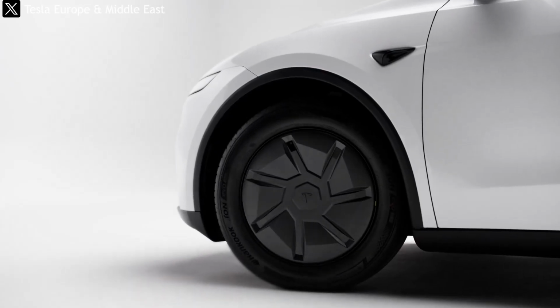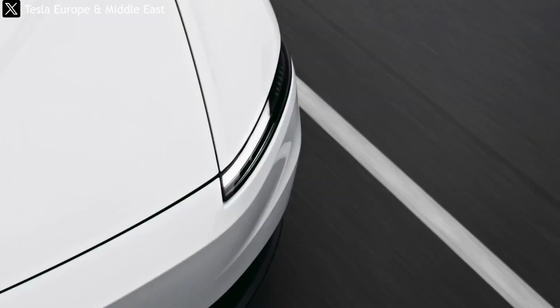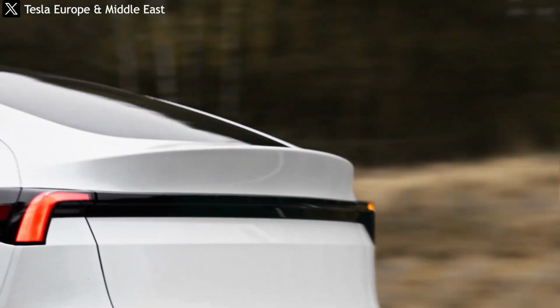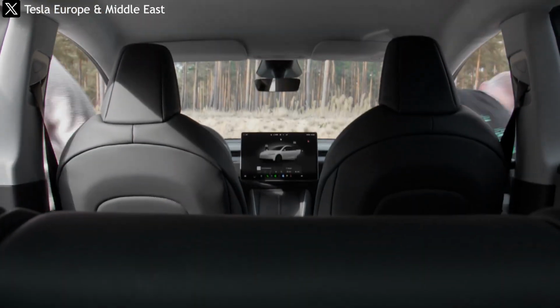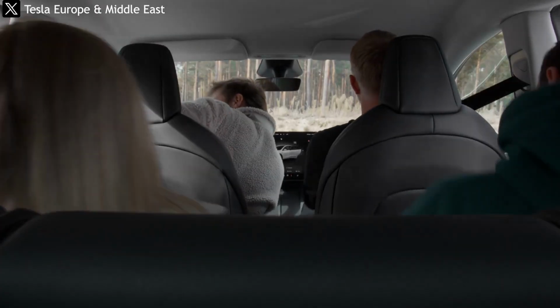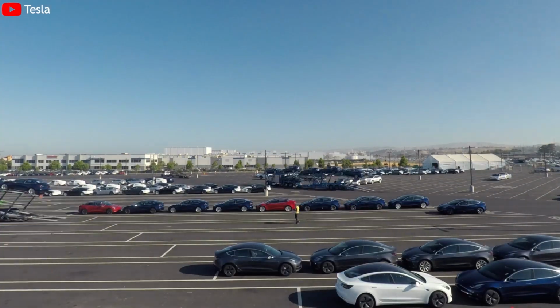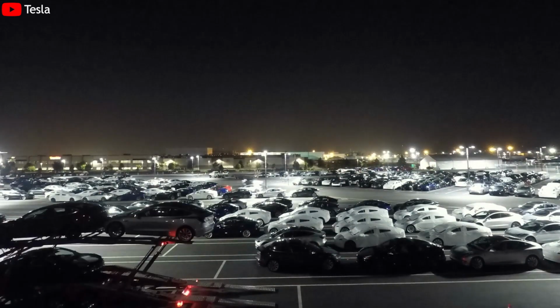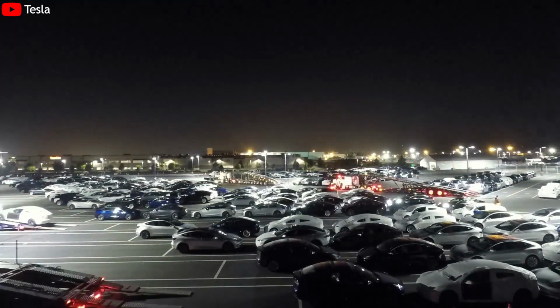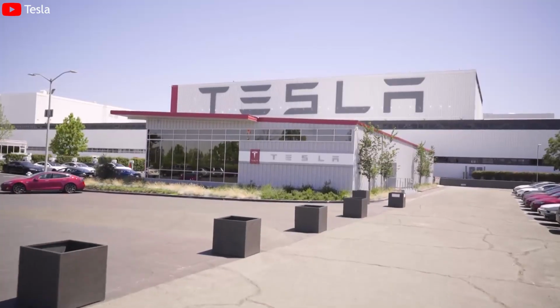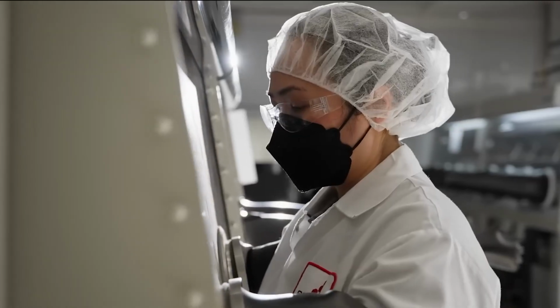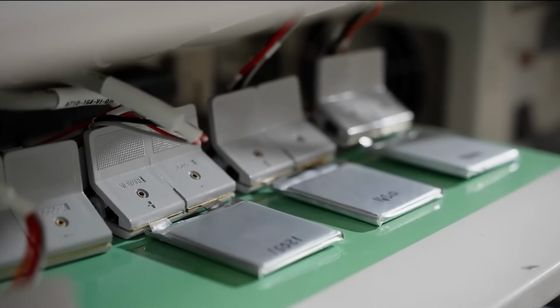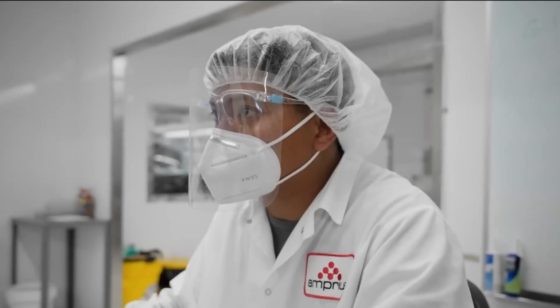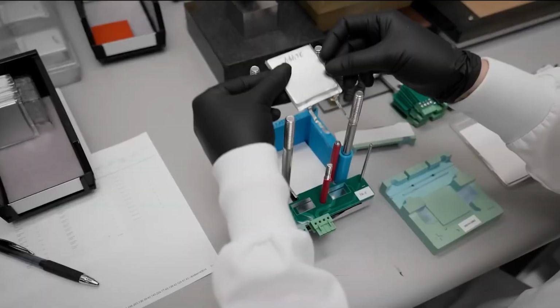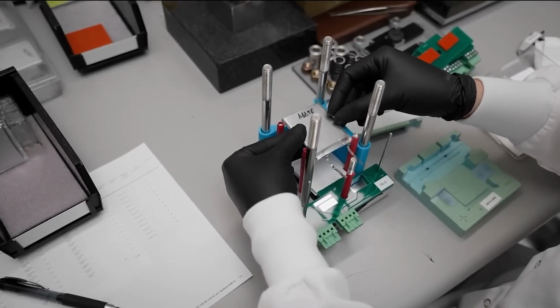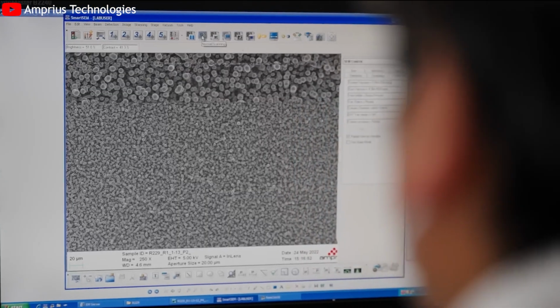In the automotive industry, a defect that emerges after 6 to 12 months in customer vehicles is more dangerous than thousands of cells scrapped inside the factory. Warranty risk, recall exposure, and brand damage cannot be offset by theoretical efficiency gains. This is where Tesla's real advantage emerges. Contrary to popular belief, Tesla did not invent dry electrodes. Solvent-free coating variants have existed for decades in niche applications where volumes were low and economic demands modest.